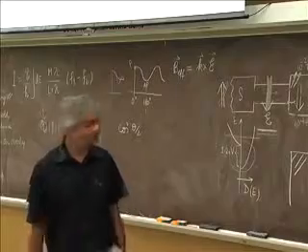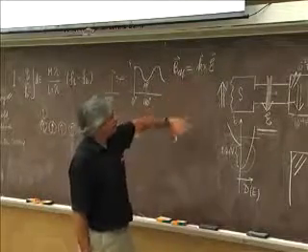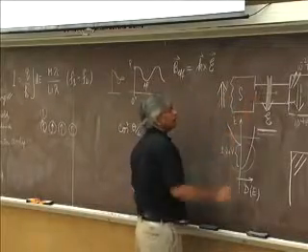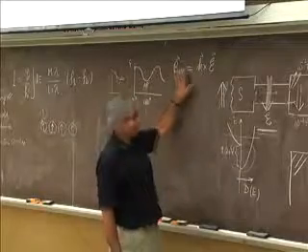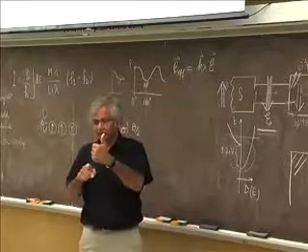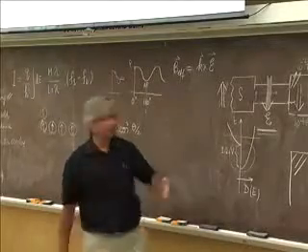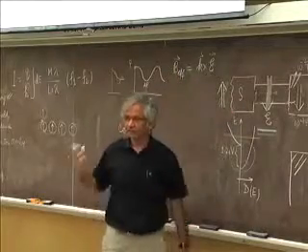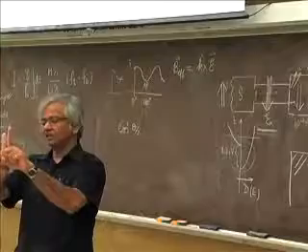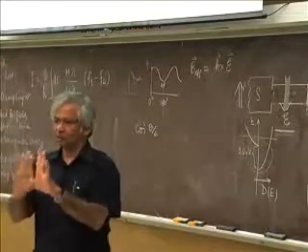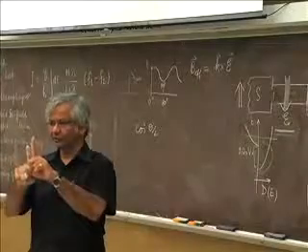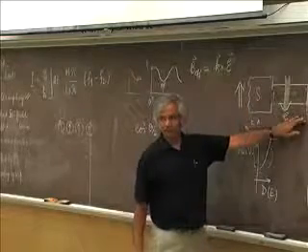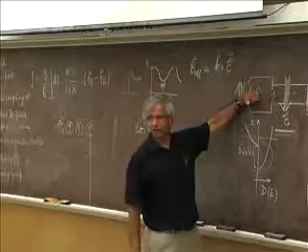Okay? And one of the convincing things they have there is that if the injected spins are in a direction perpendicular to the B field, this effective B field, then you see the effect. Whereas if you turn these magnets so that the injected spins are in the same direction as the B field, in which case they shouldn't turn, because if the B field is this way and the spins are injected this way, nothing will happen, then the oscillations go away. So they show that control experiment, that if you're in the same direction, you don't see anything. So they do the experiment with the magnets in a particular direction, and then with the magnets turned in the direction of the B field itself.